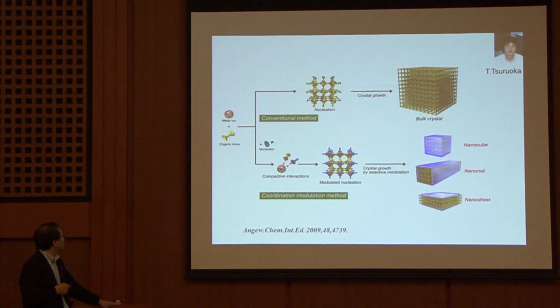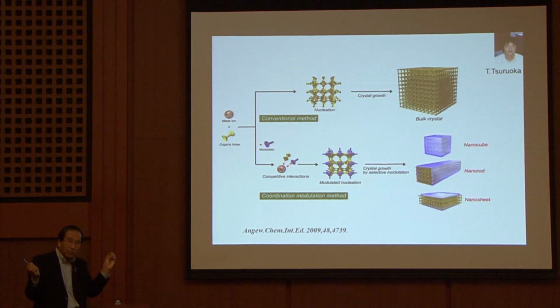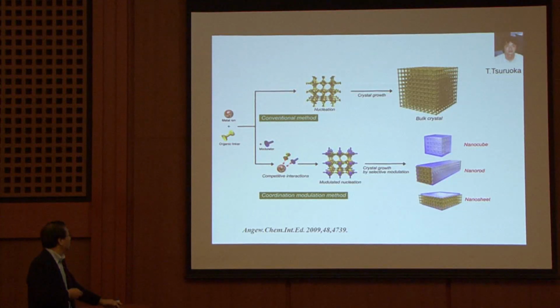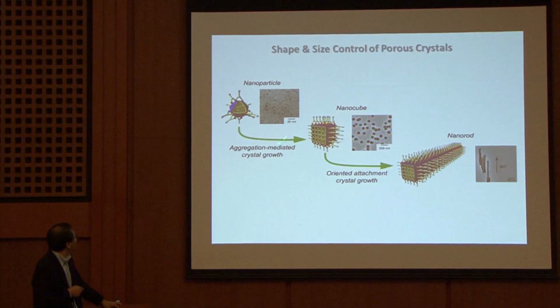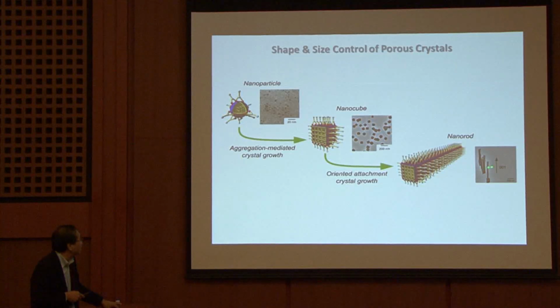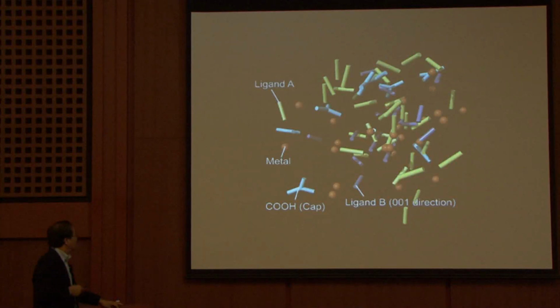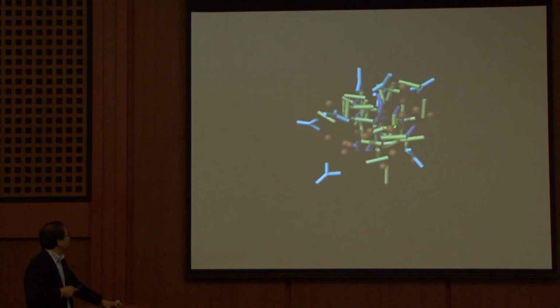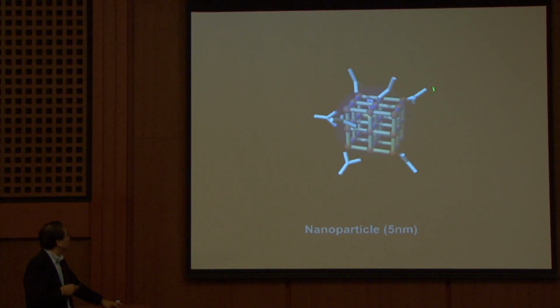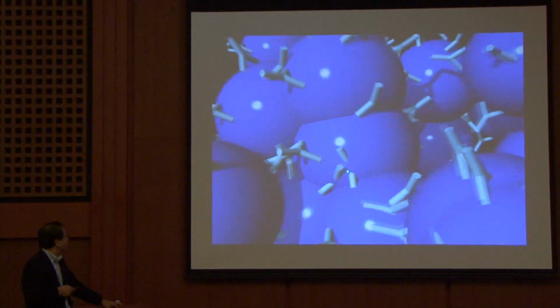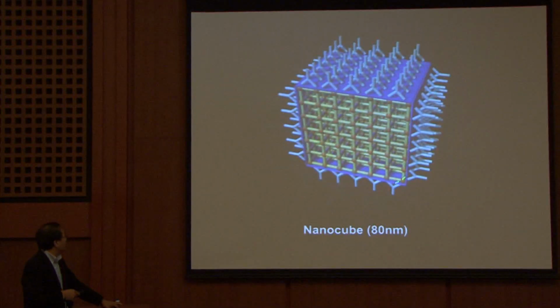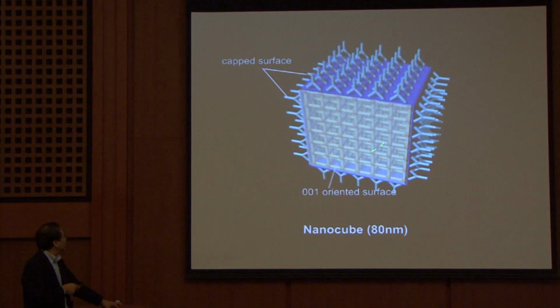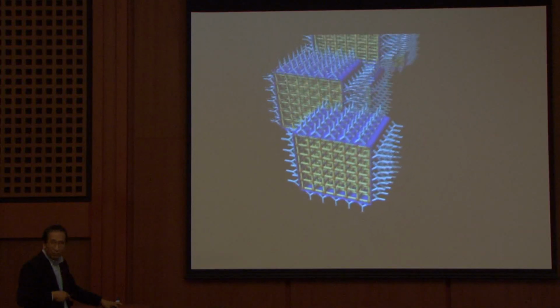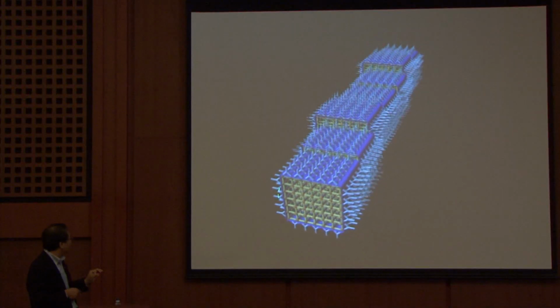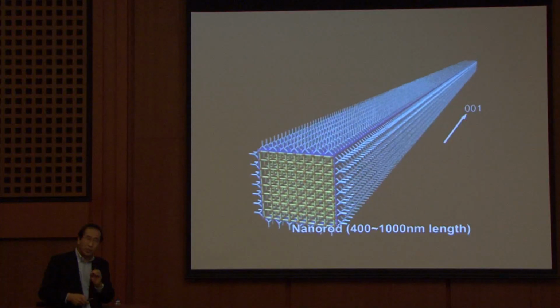But in the presence of another ligand, which we call a coordination modulator, the modulator stops the extension of crystal growth on a specific surface. This is the point. So we use the modulator to obtain these nanoparticles, nanocubes, and then nanorods. This is the idea, and we also obtained the results. The ions are linked by the yellow one, which is bidentate, and would extend more and more, but using the modulator we can stop the growth of this surface here. But still this site has a chance to give crystal growth. So we can control the size and the shape by using the modulator. This is completely a chemical process.